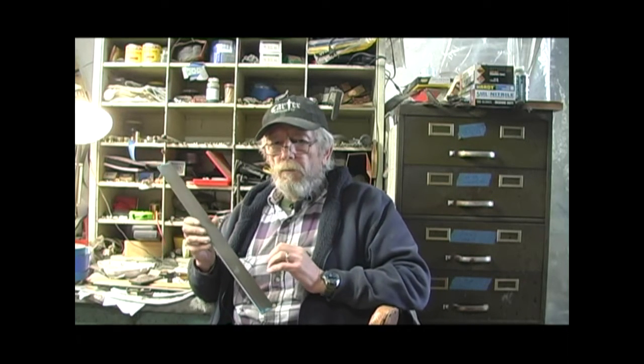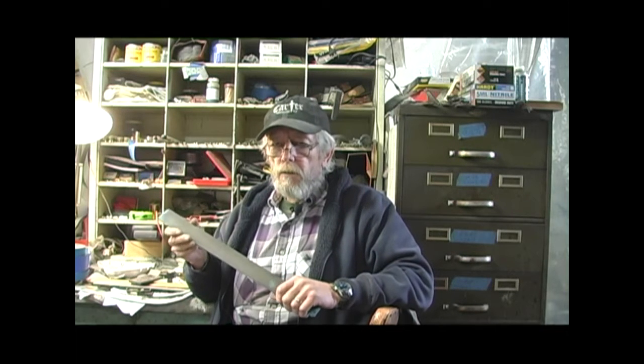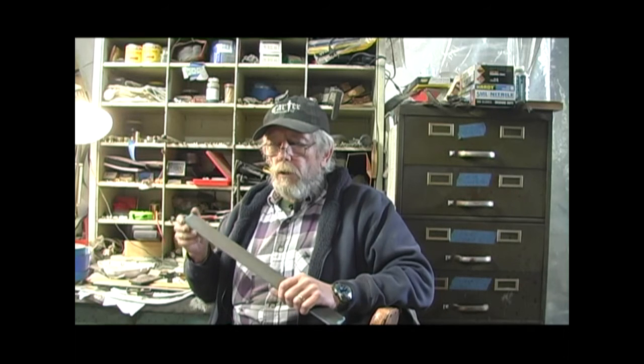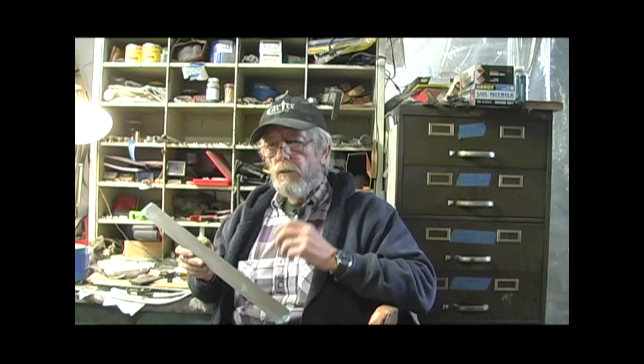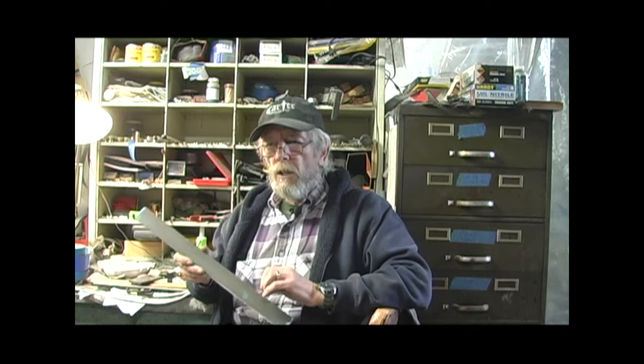You know, water quenches them very fast. It's going to cool the steel very fast. There's a risk. Sometimes it's such a shock to the steel that it will crack. Most people, if you're using a water or an oil quenching steel, quench them in warm oil, which cools them rather quickly, but not real fast. The oil is at a certain temperature where it just cools it at a certain rate. With air hardening steels, obviously they're cooling much slower. But they've learned that that's part of your heat treatment, that if it's done in a very specific way, specific temperatures, a specific quenching method, that's what's going to give you your optimum performance out of that steel.